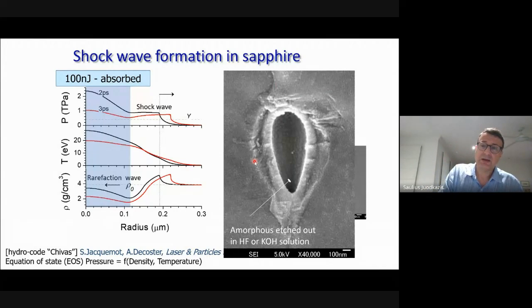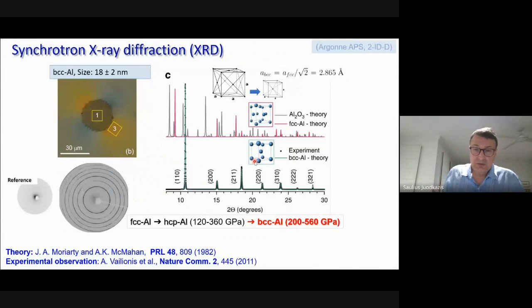This is shown here. So those conditions which we create are really extreme. We want to see what materials are inside those tiny volumes. And this was done at Argonne in the United States. We measured X-ray diffraction from the layers of modified sapphire. And what we saw was a very simple X-ray diffraction pattern, which was at first